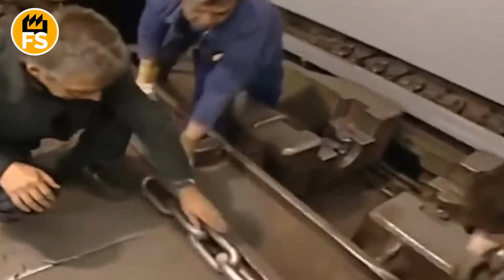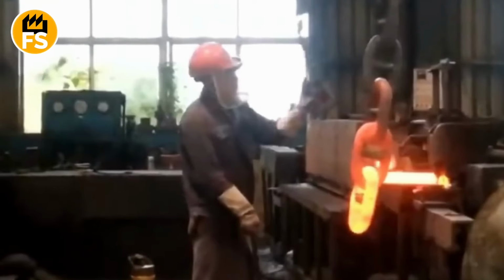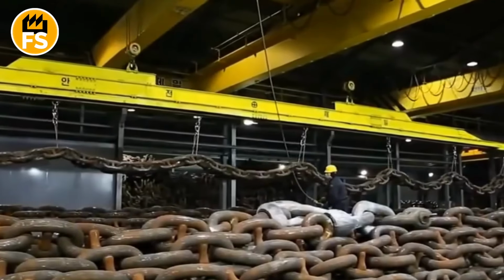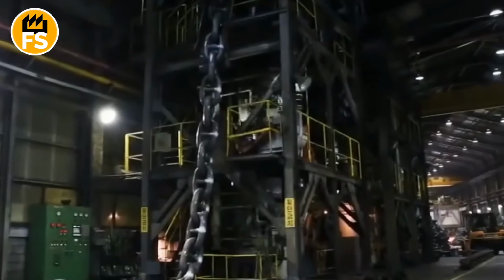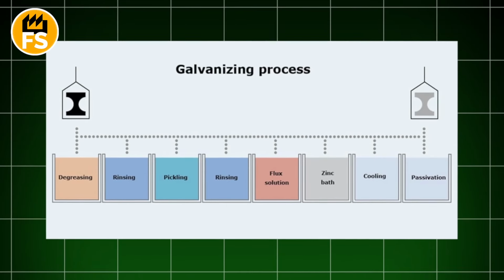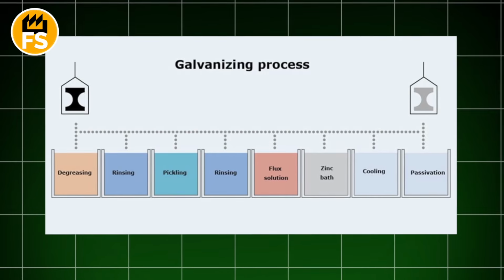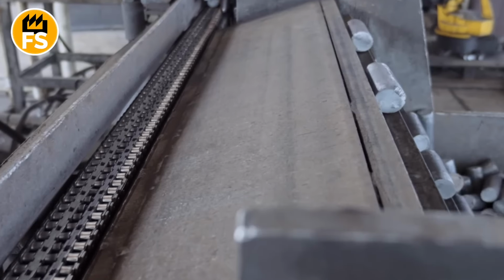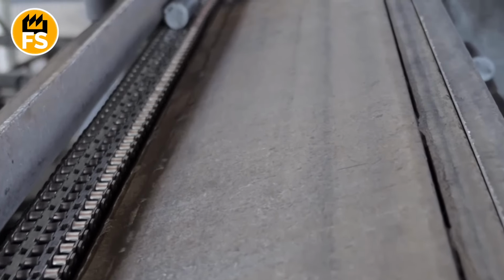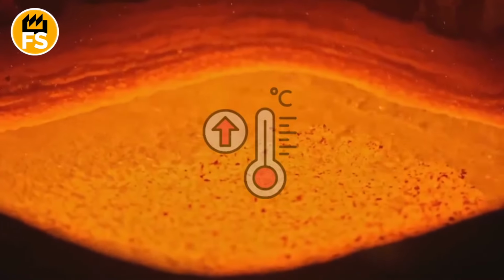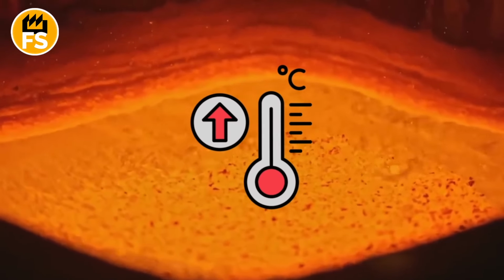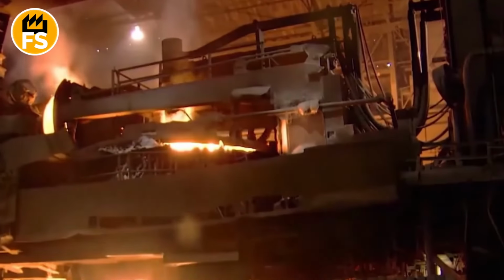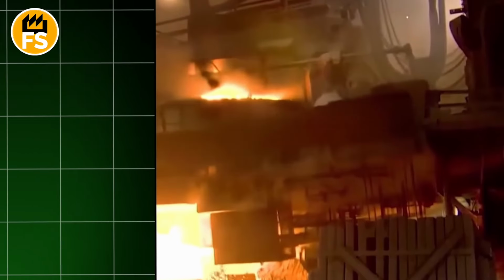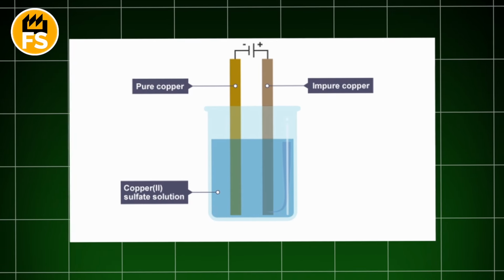In order for our chain to serve long and reliably even in difficult conditions, it needs protection from corrosion. This is where coating comes into play. The most common method is galvanizing, which can be hot dip or electroplating. In hot dip galvanizing, the chain is immersed in a bath of molten zinc at a temperature of 860 degrees Fahrenheit. Zinc, interacting with steel, forms a strong protective coating that not only prevents rust, but also has the property of self-healing for minor damages.